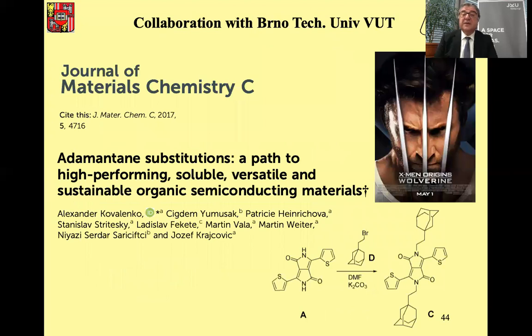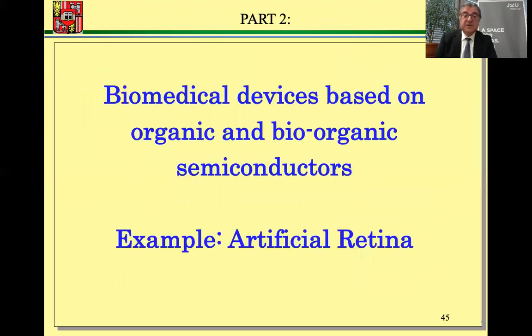And one example I want to show also, that adamantane actually is a side group which stabilizes these materials even further. And these materials, which are hydrogen bonded materials, can be substituted and can be more stabilized in the side chain. So now these are the so-called hydrogen bonded semiconductors, which we introduce now into the biomedical devices and in general is processing of these materials for biomedical applications. And here is an example with artificial retina.